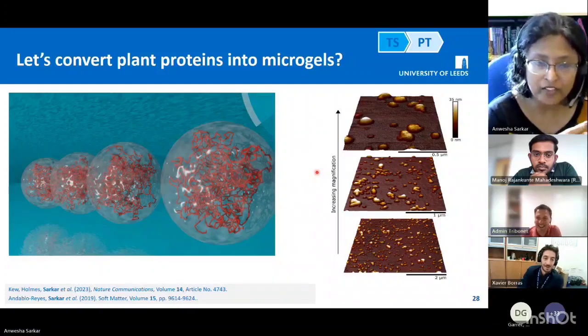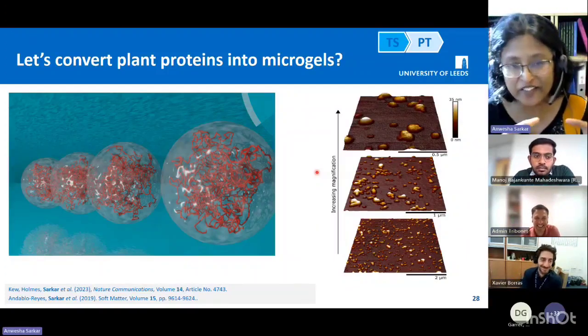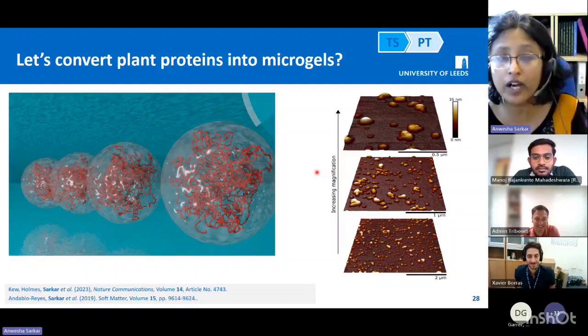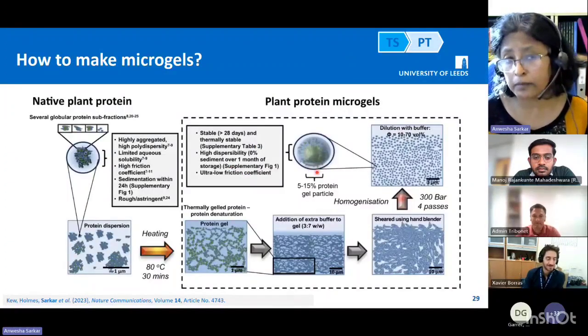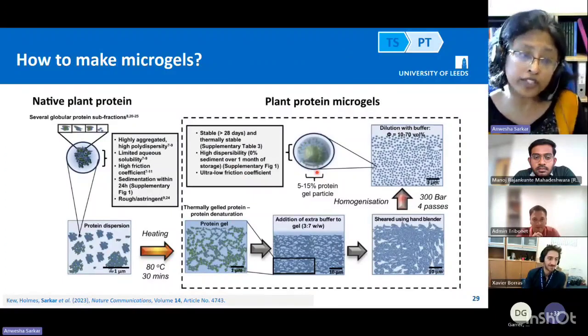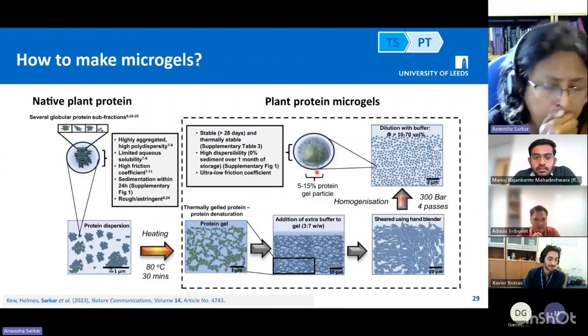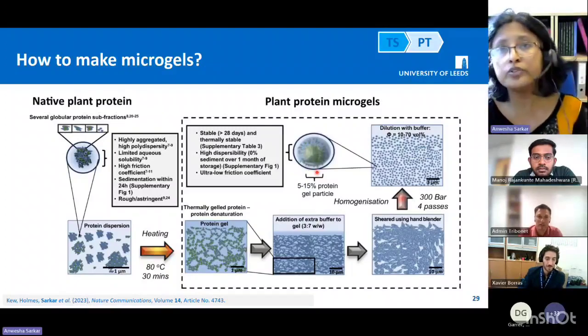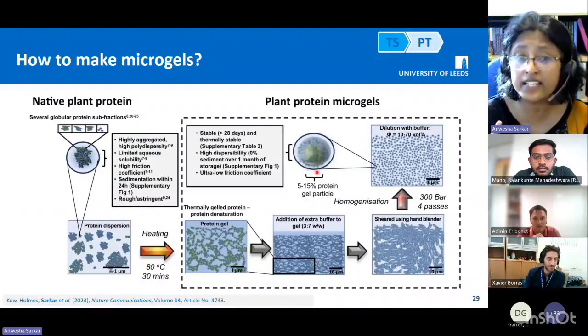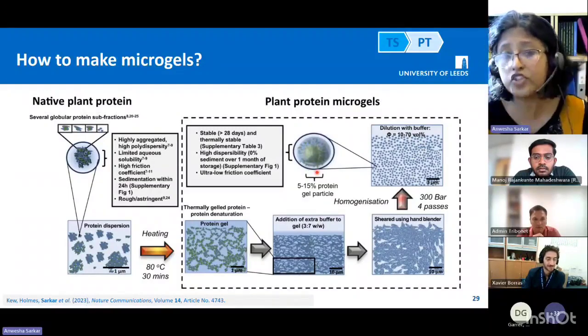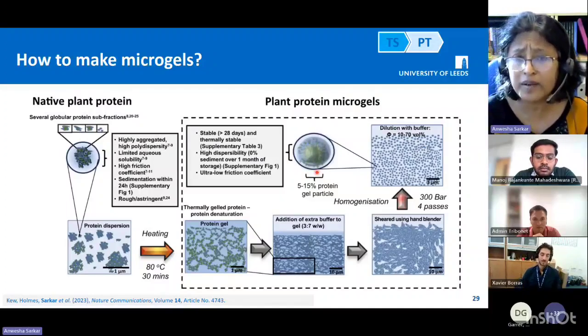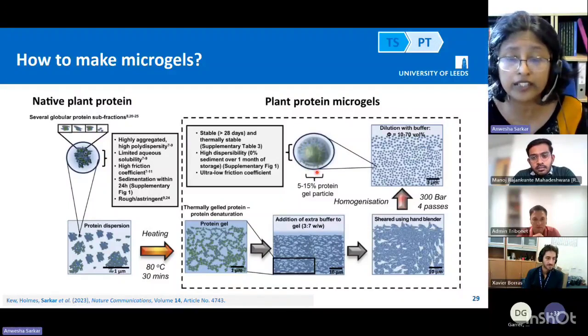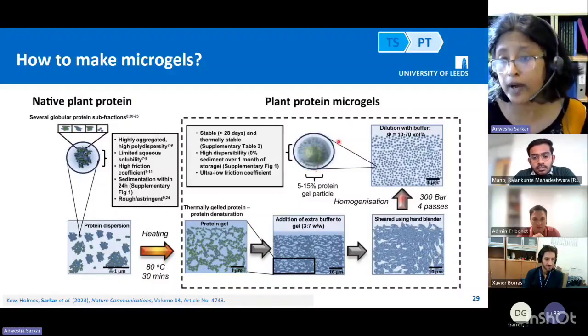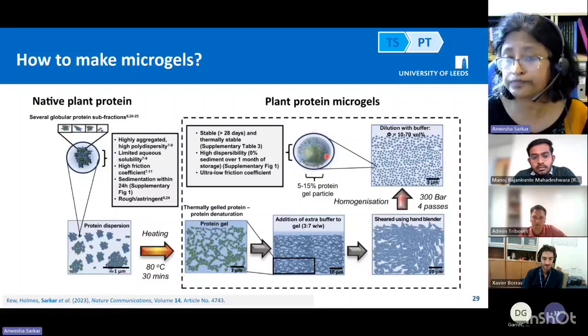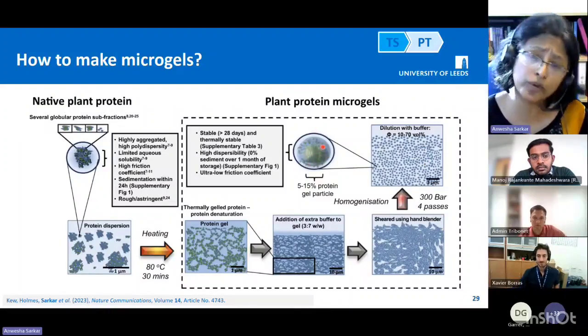No problem. So what we can see here is, yes, we can take a plant protein and convert it into a hydrated mass. So that's the whole point. So here you can see how we can make microgels. You actually use the plant protein and their inherent cysteine chemistry and heat treat them to form these gels. So essentially they contain mostly water and very, very little protein. And then you can make these gels and shear them up using blenders to form these microgels. And you can change their volume fraction, deformability, and so on.